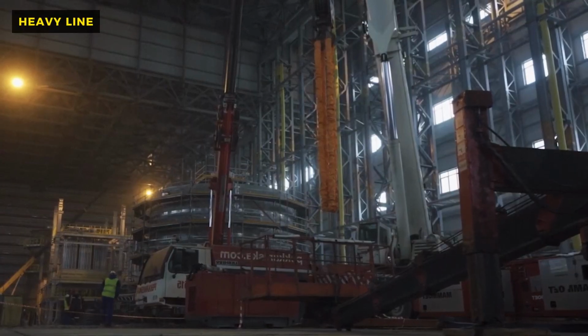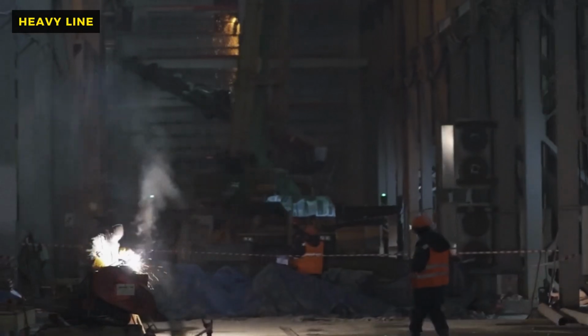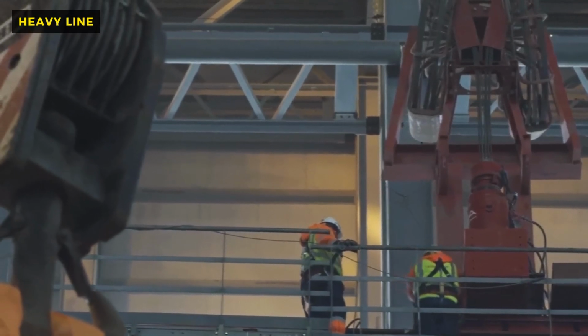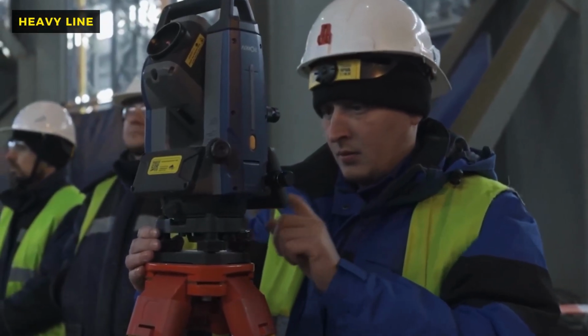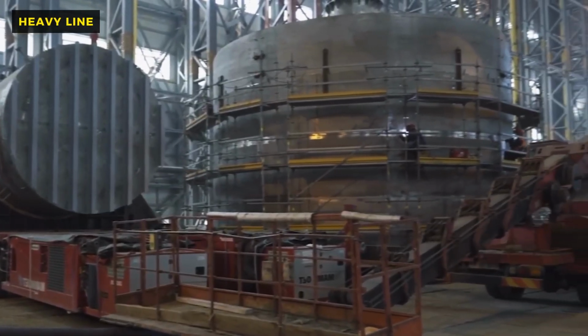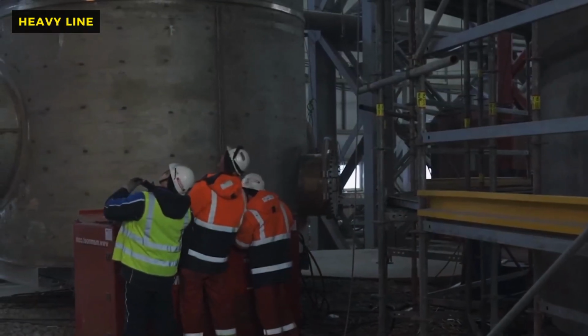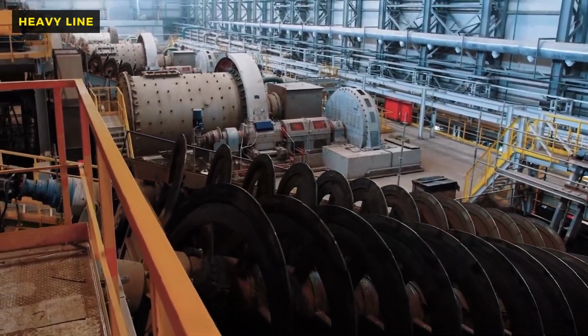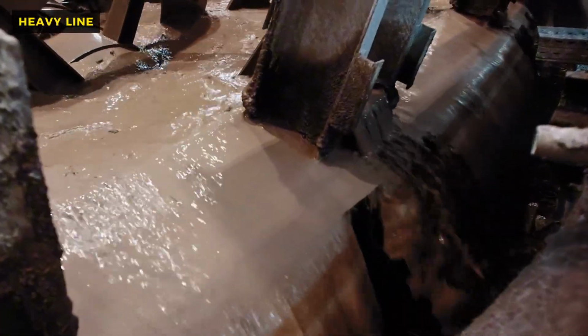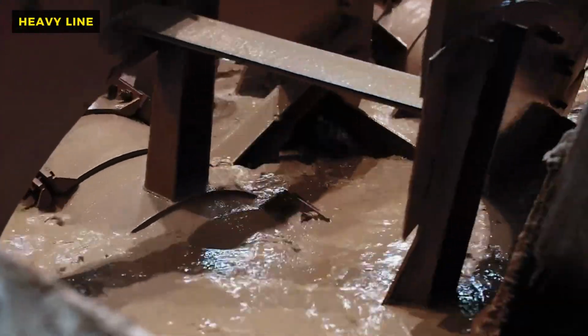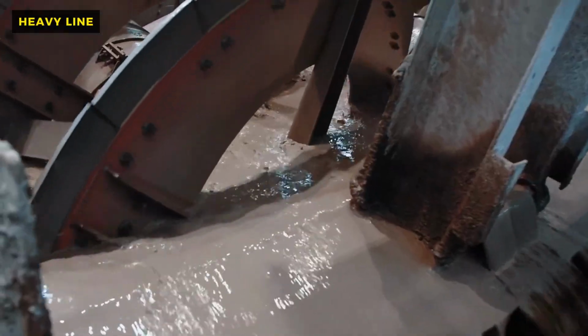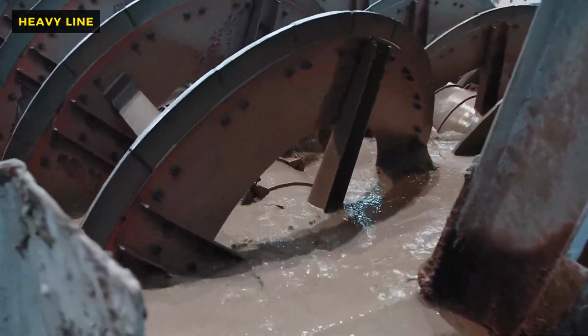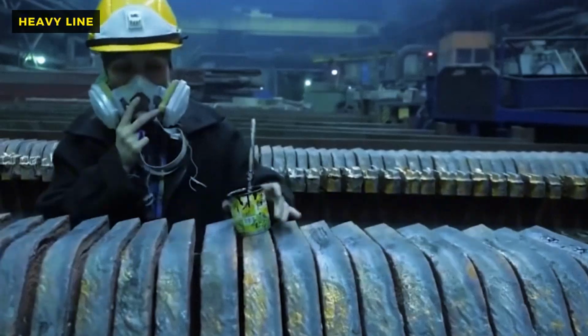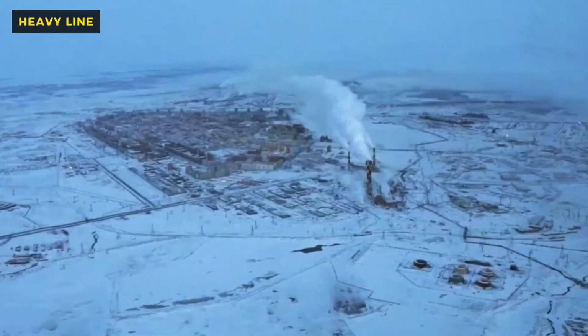Once the matte, the mixture of nickel and copper sulfides, is tapped from the flash furnace, it is still far from pure. It is transferred into Pierce-Smith converters, which look like massive horizontal cylinders lying on their sides. These vessels, easily 10 meters long and 4 meters in diameter, are mounted on trunnions that allow them to rotate. The converter is charged with the molten matte, and silica flux is added. Then a row of tuyères, pipes entering the side of the cylinder, blasts air into the liquid bath.